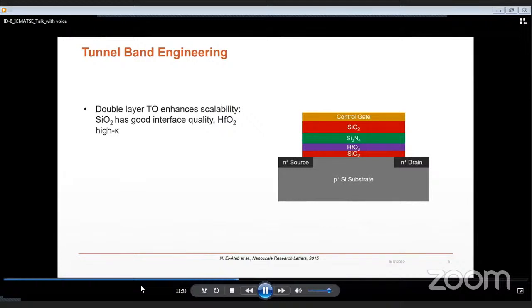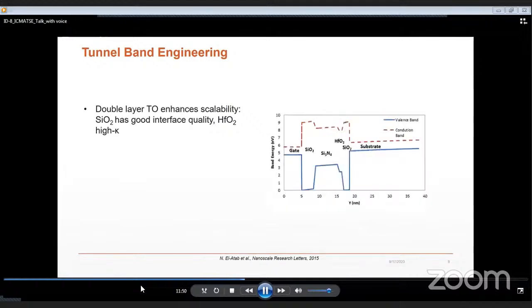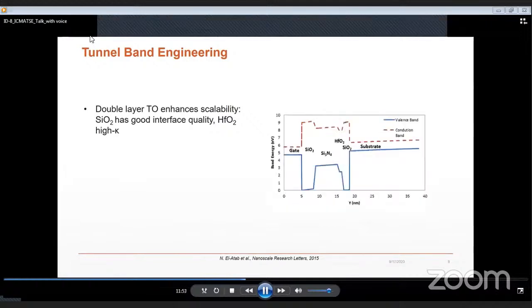So in order to understand the benefits of the double layer tunnel oxide, I studied a structure that includes a silicon nitride charge-trapping layer with double layers of silicon dioxide and hafnium dioxide as tunnel oxides, and compared it to the case of a memory with a single tunnel oxide. If we consider the energy band diagram of the structure, we can clearly see that the hafnium dioxide, with a high K, results in a much lower barrier for the trapped charges in the silicon nitride layer than in the case of the silicon dioxide. And so if hafnium dioxide is used as a single tunnel oxide, the trapped electrons could more easily leak back, degrading the retention characteristic of the memory.